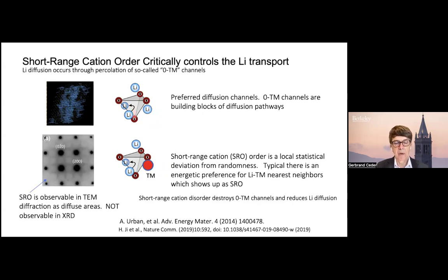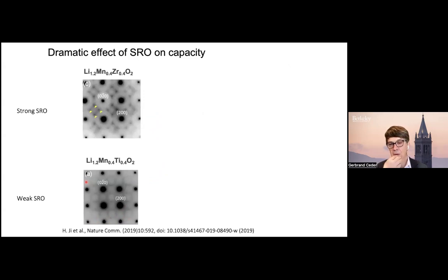And the way you see short-range order is extremely hard to detect in XRD, but you clearly see it in electron diffraction in TEM, and it's typically seen as this kind of diffuse scattering between the Bragg peaks. You can also see it in single crystal XRD, but of course that's a lot harder to do. So I'm going to show you a dramatic effect of short-range order.